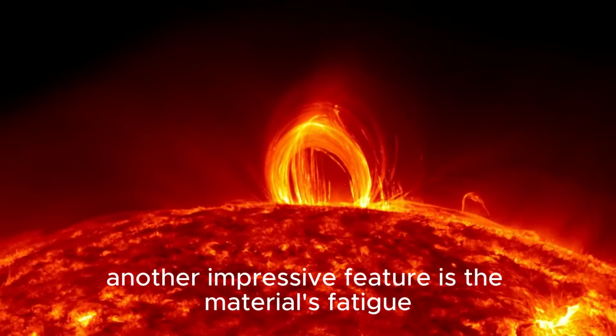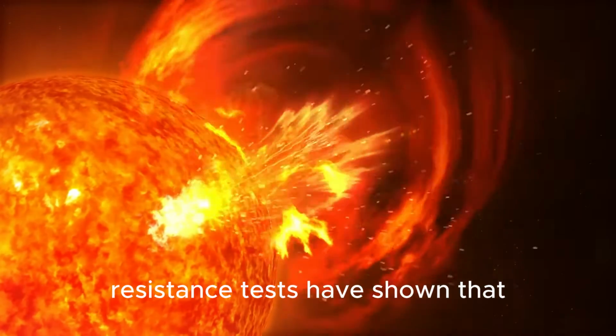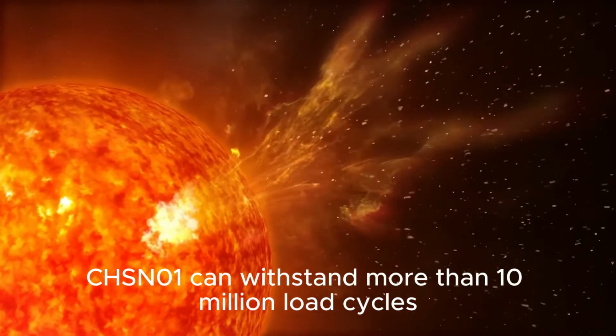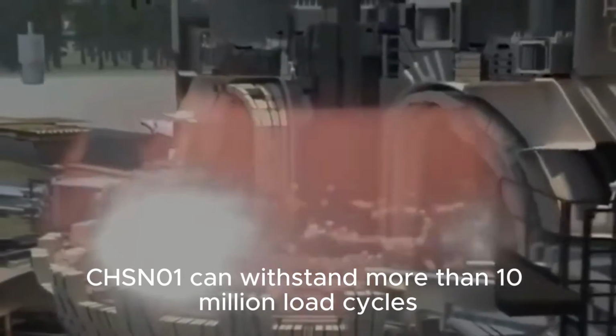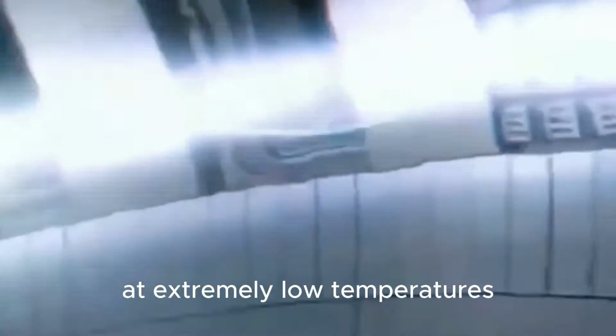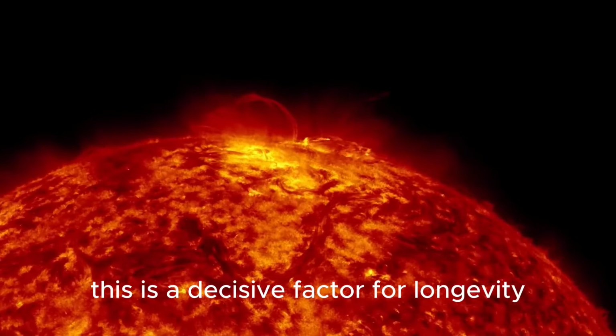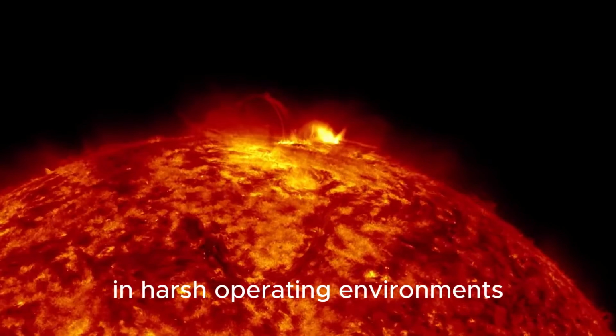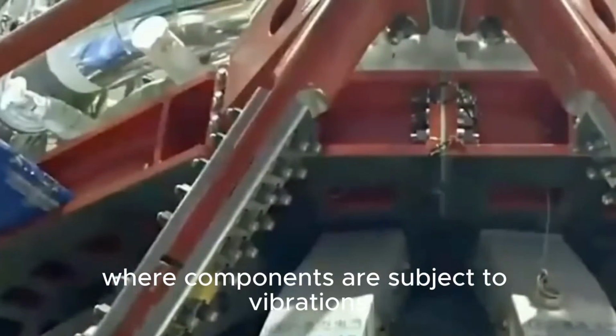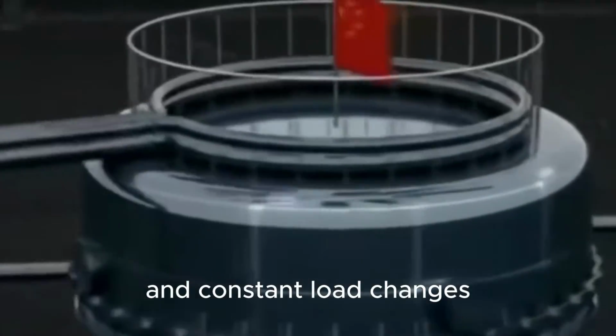Another impressive feature is the material's fatigue resistance. Tests have shown that CHSN-01 can withstand more than 10 million load cycles at extremely low temperatures without developing microcracks, 2 to 3 times better than 316LN. This is a decisive factor for longevity in harsh operating environments where components are subject to vibrations and constant load changes.